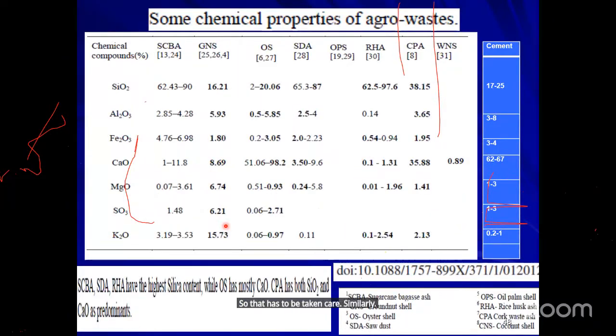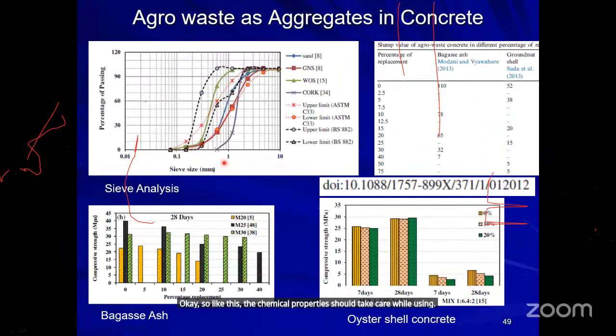Similarly, chemical properties wise, cement has silicon dioxide 17 to 25%, Al2O3 3 to 8%, calcium oxide 62 to 67%. So you can see even in sugarcane bagasse ash, SiO2 is 62%. Similarly, groundnut shell 16.2, almost similar to cement. So like this, we should take care of the chemical properties while using these, because these chemical things will affect the durability of the system.